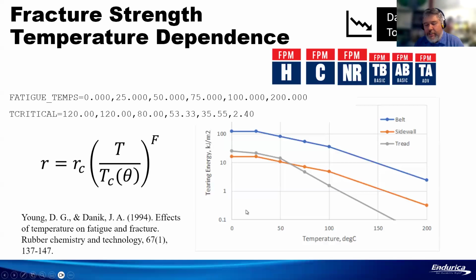This is just a plot that shows the dependence of the tear strength of the rubber on temperature up to 200 C for the belt, the sidewall, and the tread of the tire. And you can see that there's some rankings. Some of the rubbers are more sensitive to temperature, some of them are less sensitive. And so that's an important part of this calculation that involves very high operating temperatures.